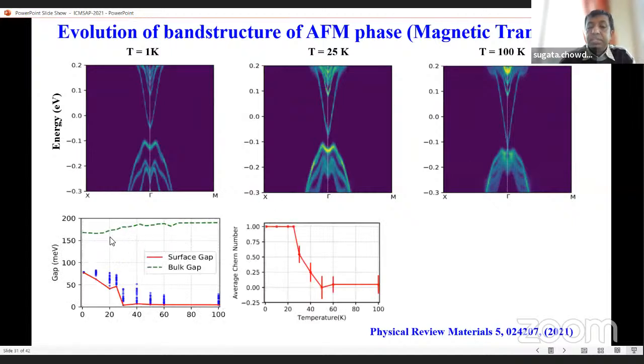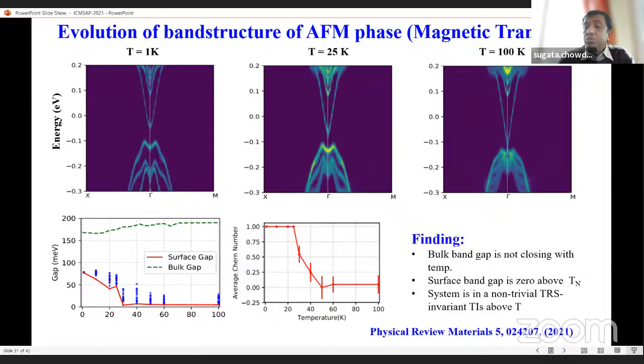So this is showing the surface state. The surface state is going to zero as the temperature is increasing, but the bulk gap is consistent, and also the average Chern number is changing with the temperature. So the finding is that the bulk gap does not close with the temperature, but the surface band gap is zero above the transition temperature. The system is non-trivial, and the system is a non-trivial TRS invariant above the transition temperature. So in this case, we are getting that expected theoretical result.